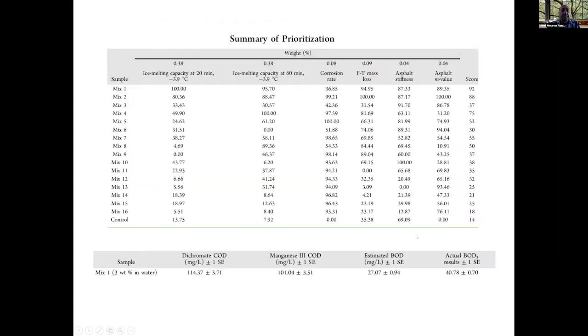a good sign. And I have not shown every graph, just here in this table I give you the normalized properties of these deicers. In ice melting, we measured ice melting capacity at -4 Celsius at 20 minutes and 60 minutes using the standard test protocol. And also we measured the corrosion rate, we measured the freeze thaw mass loss, and we measured low temperature asphalt stiffness and the low temperature asphalt M value for the asphalt exposed to these deicers.